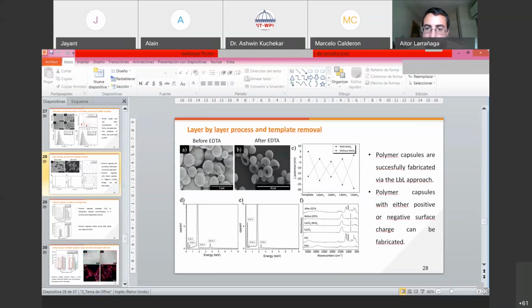No, but they changed the sign, right? Yeah. This is something that I, to be honest, didn't realize. It is something that I have to check better because I was not aware of that. But yeah, there might be a slight change that can be because of the presence of manganese dioxide nanoparticles that are somehow interacting. I have to say also that checking the zeta potential of these layer-by-layer capsules became quite tricky as you increase the number of layers. So there is always an interaction between the previously deposited layer and the layer on the surface. So if you really want to check that, you have to be very careful with the conditions at which you perform the experiment.